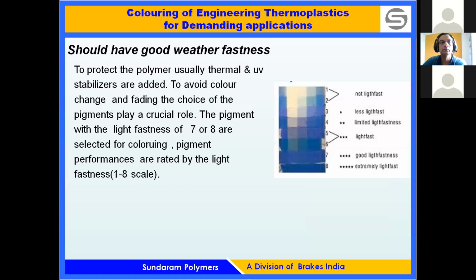Should have very good weather fastness. To protect the polymer, usually thermal and UV stabilizers are added, while to avoid color change and fading, the choice of the pigments plays a crucial role. Pigments with a light fastness of 7 or 8 are selected for coloring. Pigment performance is rated on a light fastness scale of 1 to 8. You can see in the picture the difference between the light fastness rating of 1 and 8. Normally we use grades of 7 and 8, which can withstand weather conditions and are stringent enough for long-lasting use also.